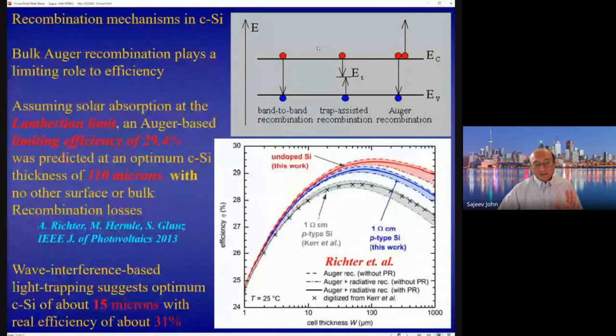So no matter how high a quality of silicon you create, you cannot get rid of this Auger recombination, so this is considered intrinsic. So about 10 years ago, a group in Germany, co-authors here, Richter et al., defined what they thought would be an efficiency limit to silicon solar cells based on the assumption that the maximum amount of light you could absorb is given by the Lambertian limit, and that one has only this intrinsic Auger recombination loss. So here's a plot of efficiency that they made versus the thickness of the solar cell.